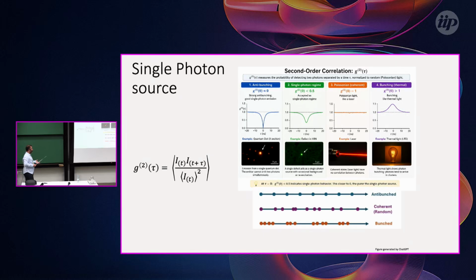Basically, what we are trying to do, if you're using a correlation setup, is calculate what we call G2, and this G2 for a single photon source will give you the probability of emitting more than one photon at a time. And basically, by looking at the photon statistics, we can describe these light sources in three different groups. The first one, if its G2 value equals 0, we will say that this is anti-bunching behavior. This means that every time you press a button, only one photon will come from this light source. Generally, this is for ideal sources with G2 equals 0, but in general, we have a lot of problems with these quantum dots.